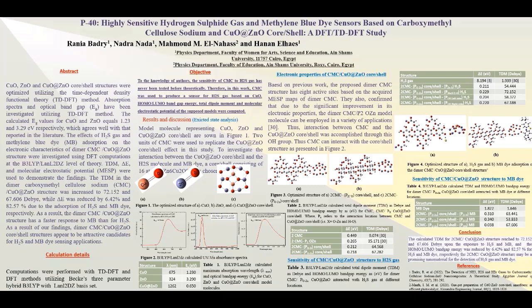Our conclusion is that as the total dipole moment of CMC and copper oxide zinc oxide structure increases and the HOMO-LUMO band gap energy decreases upon the exposure to the H2S gas and methylene blue dye, it can be concluded that the proposed structure of CMC and the core shell may be a promising material for the detection of H2S gas and methylene blue dye.